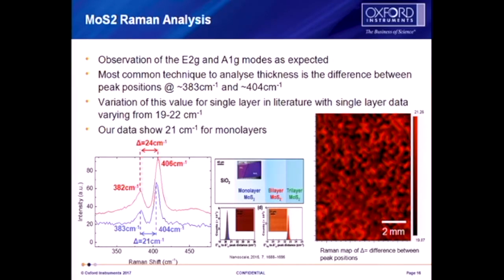Again, Raman is used, and Mike alluded to it earlier, that he didn't understand the wave numbers. But where you're looking here, if you've got a single atomic layer of molybdenum disulfide, you get a difference between the two peaks of 21, which is here. That's the classical one. So somewhere between 21 to 22 wave numbers is very indicative of single layer molybdenum disulfide. Above that, 24 is, I believe, a dual layer, and above that it's either triple or quadruple. It doesn't change very much above those numbers. Of course, we have to go and check this out to make sure we've got the monolayer of molybdenum disulfide.